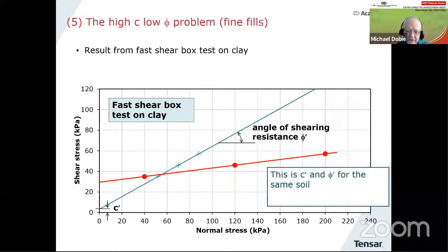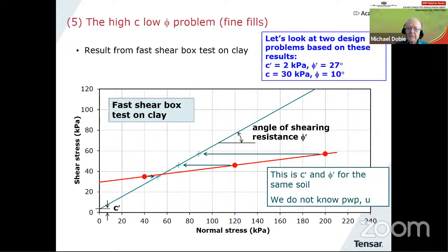We need to have results like this, in this case maybe carried out by a slow shear box test, and that would be a typical result for a fine soil. So why is there a difference? Well, the distances between those data points are the pore pressures. At the high stresses, we get positive pore pressure, and at the low stresses, we get negative pore pressures. Because of that, it turns the envelope and gives us the red one, whereas what we really want to have is the blue one. And that would give us the right kind of properties. Sometimes I talk about this and it remains difficult to convince people.